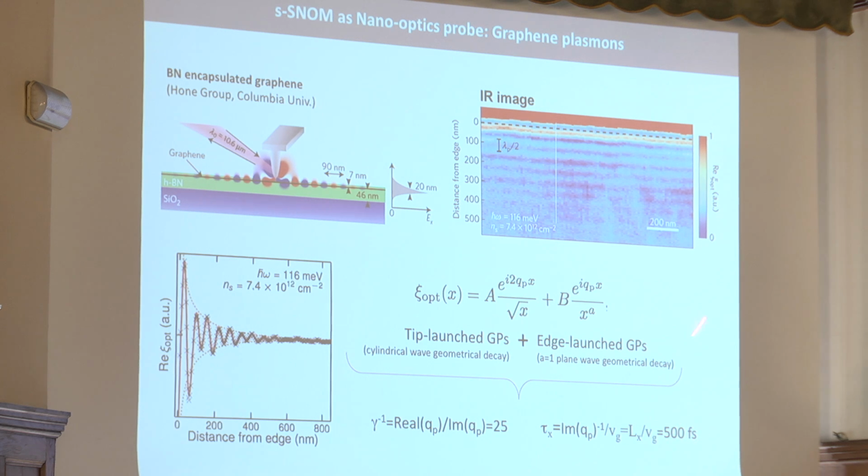And we saw that it is 500 femtoseconds for this graphene. Remember, I said that for plasmons in metals it was 10 femtoseconds. Now we have 500 femtoseconds. That is quite an improvement. Okay, nice. They can be tuned. They are much more long-lived. They are on a surface where you can put things and maybe sense them.